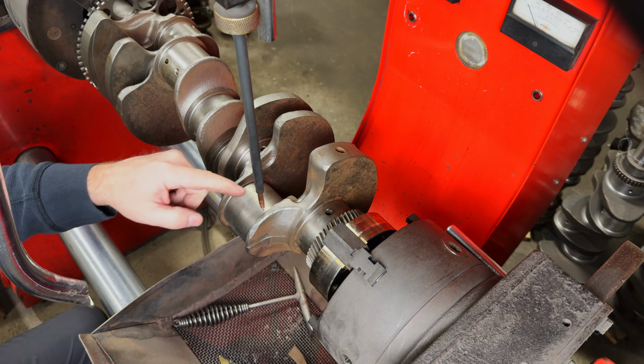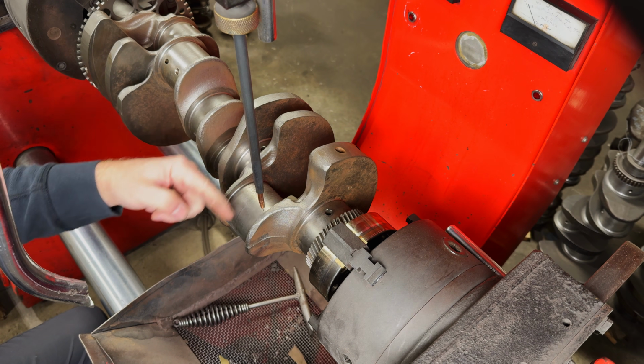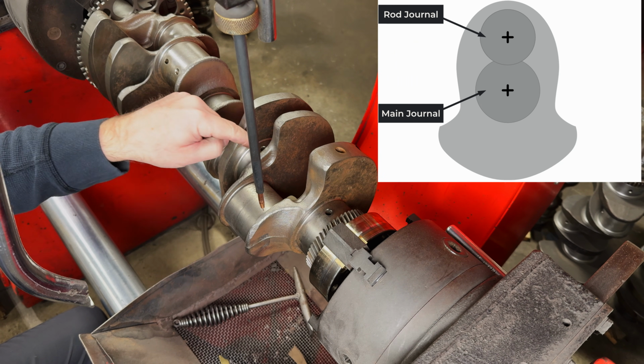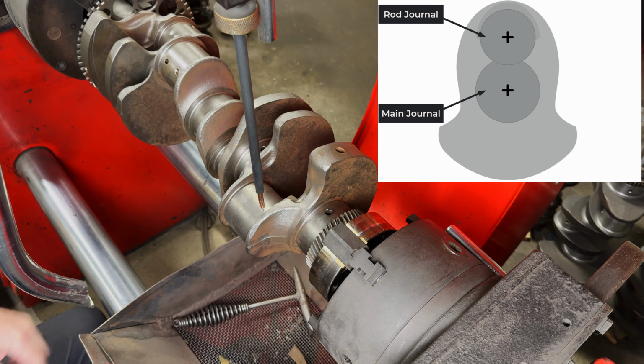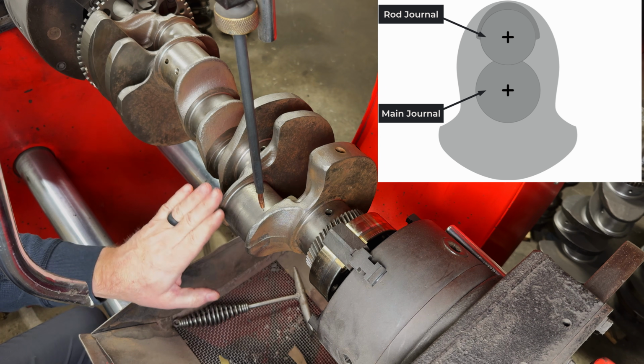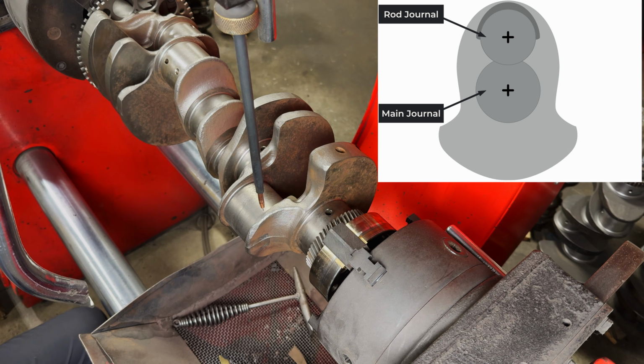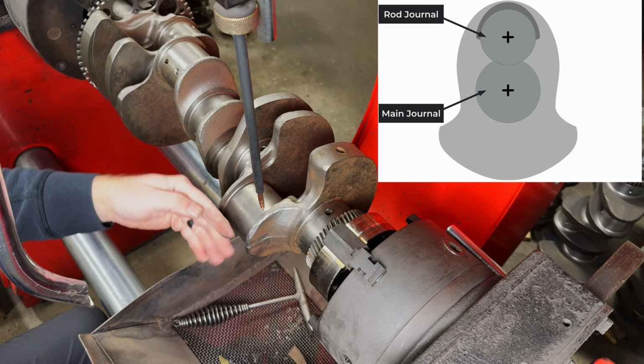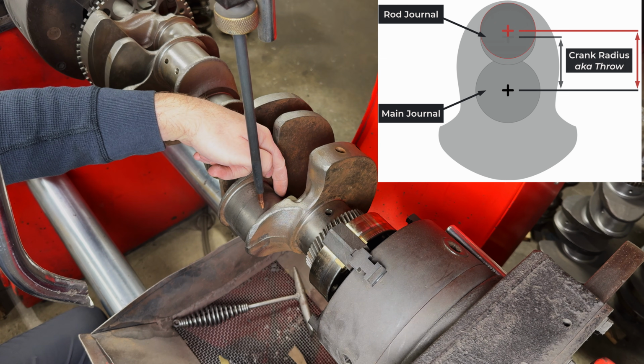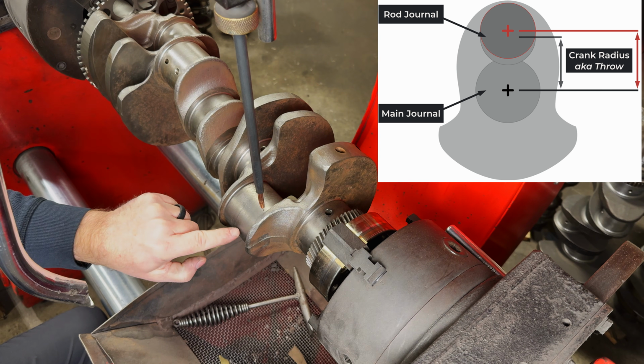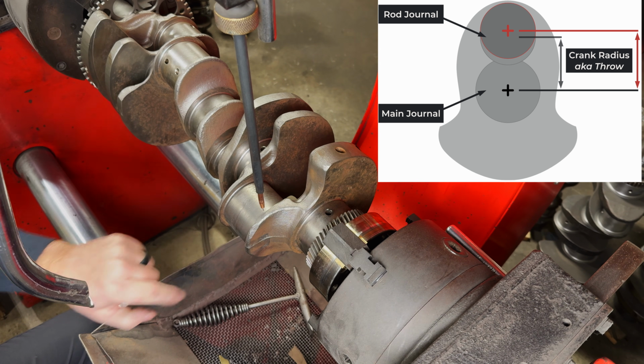So we need to add material to the far side of the rod journal, and that's why we're welding this crank. We're building up the far side, the side away from the main center line, by stacking up layers of weld. Then we'll offset grind the crank. That combination moves the rod journal center line outward and increases the stroke.